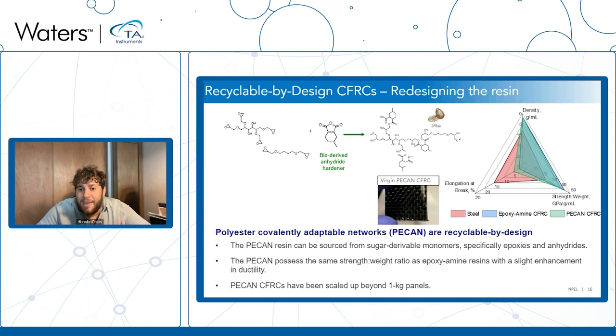So when we make a pecan-based carbon fiber reinforced composite, you can see that we have a low density, high strength to weight ratio material, and a material with moderate elongations at break. Meanwhile, when we make an epoxy-amine carbon fiber reinforced composite, we can still get a lightweight material with high strength to weight ratios and a slightly more brittle material.